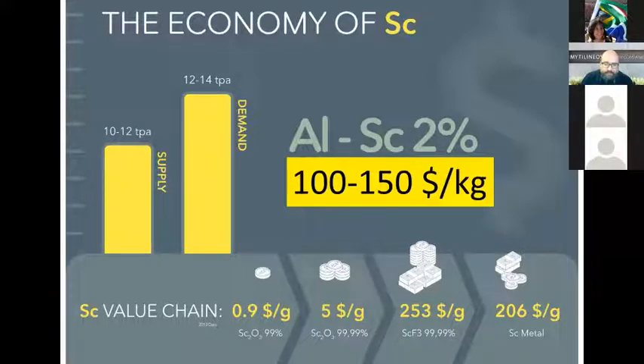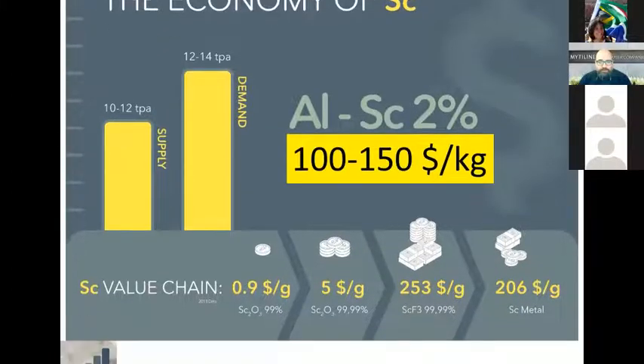So 1 gram of scandium oxide, just of 99% purity, could be charged for $1. And the metal, scandium metal, could be even $200 per gram. And more importantly, the aluminium scandium master alloy that is used to make this magnesium 3D printing powders is valued between $100 and $150 per kilogram. Scandium is not traded in the markets, so all these prices are very volatile and very uncontrolled, and they depend on trading deals between the parties involved.